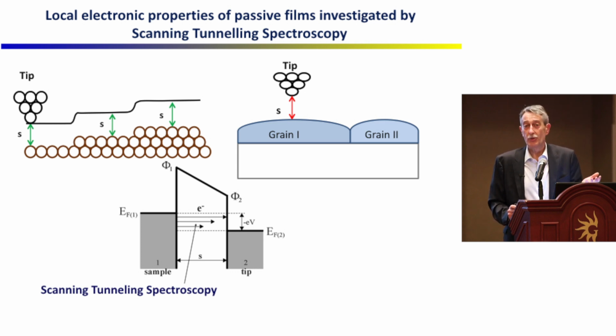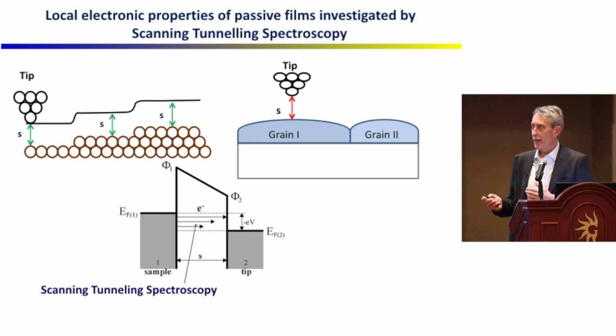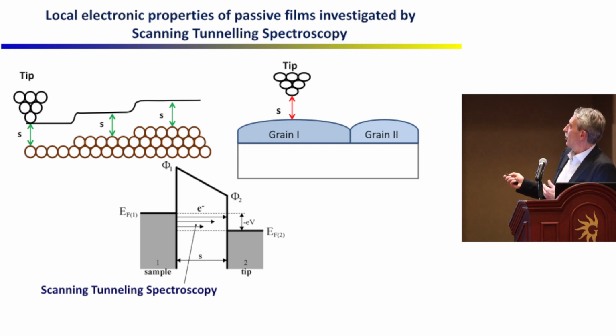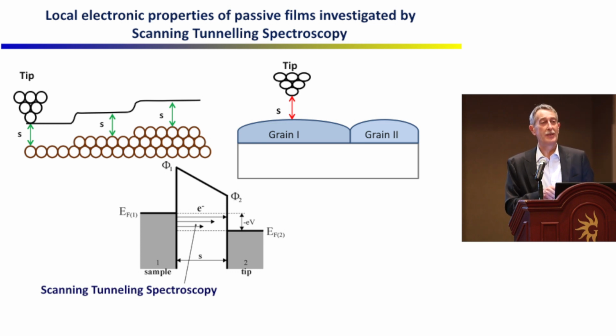And there is virtually no technique that can answer this question, except if you use the tip of the STM. At each position, you stop the scanning, and then you ramp the potential between the tip and the surface. So now you are no longer doing scanning tunneling microscopy, but scanning tunneling spectroscopy. At any point of the surface, we can record the density of electronic states with the resolution of the scanning tunneling microscope, which means better than a nanometer. So we can really look at grain boundaries.